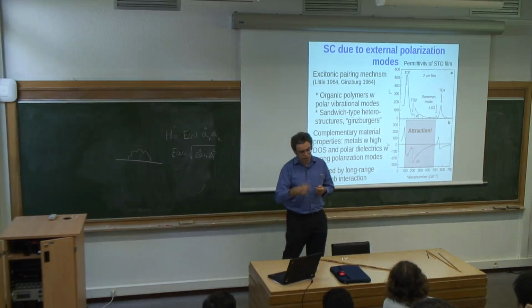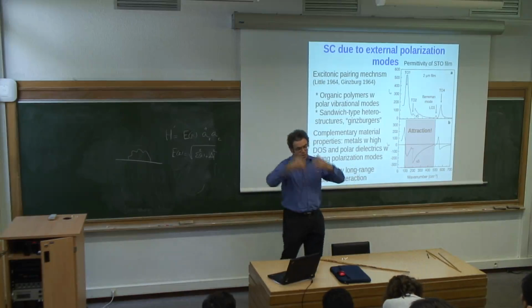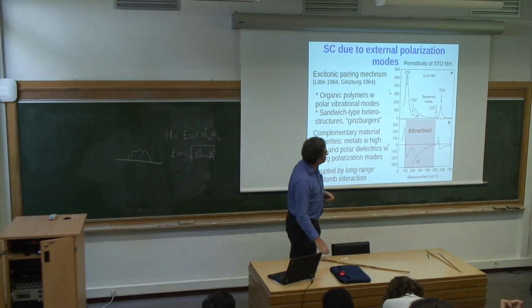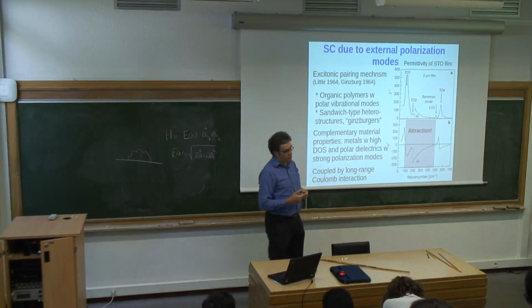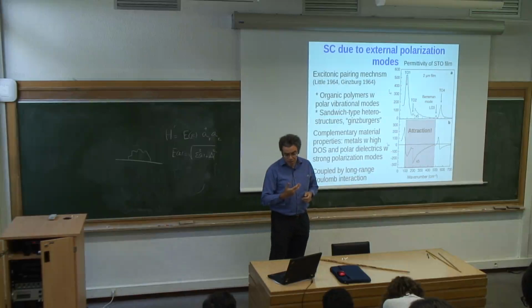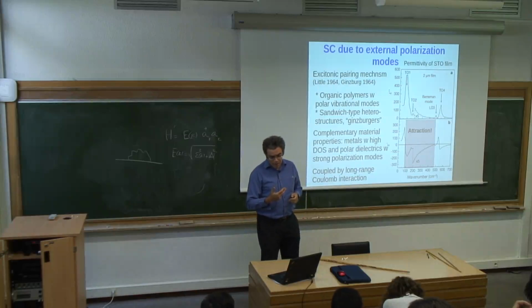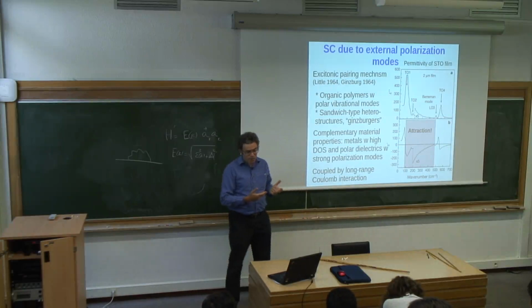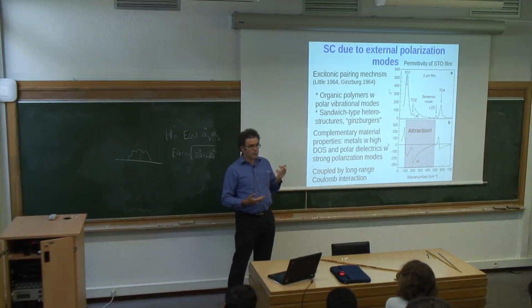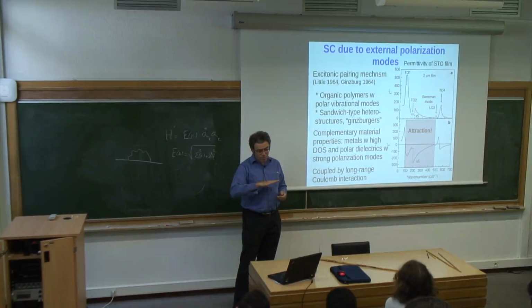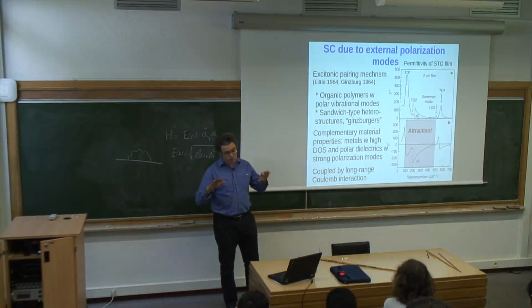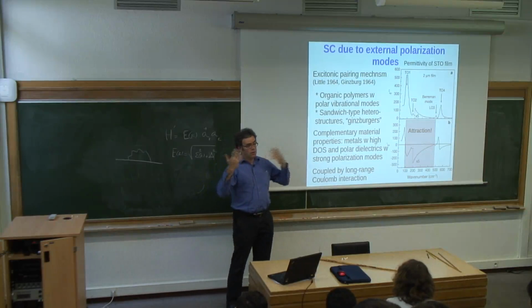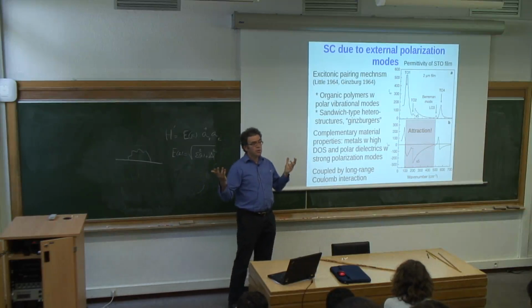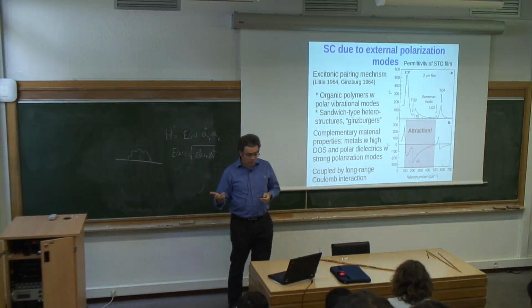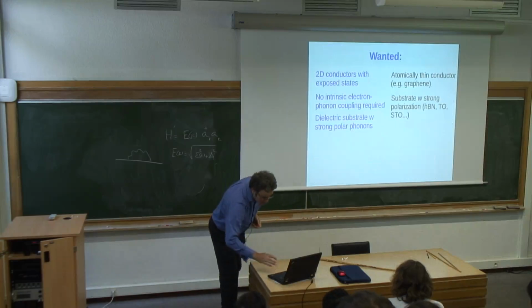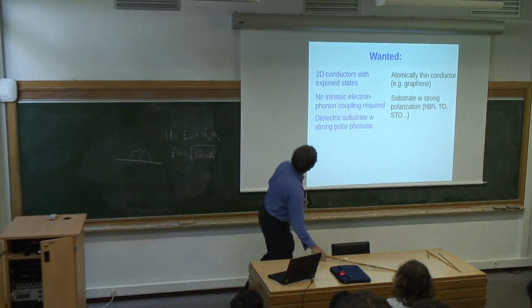So the electrons in niobium, even if you surround it with the best polar substrate available, won't see much, they won't couple much to that substrate. So it's really the case where I think the idea is good, but it was too early for its time, because at the time, really two-dimensional materials with electronic states that would be fully exposed to couple to the environment were not available, and of course they're available now, which is why I'm talking about it.